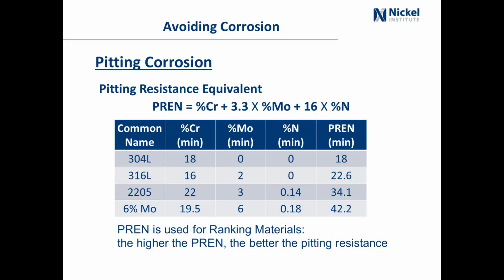There have been a number of different formulas created for PREN. This is generally the most widely accepted. There's nothing wrong with the other ones, but this is the one that is generally used. There's a slightly different formula for duplex, but it doesn't change the ranking. If you use the duplex formula on these, you might get slightly different numbers, but everything would still be ranked the same. It's only a number to be able to rank the steels, and we know then that a 6 moly is better than any of the other 3 above it, and that 304 is the least corrosion resistant, at least with regards to pitting corrosion.